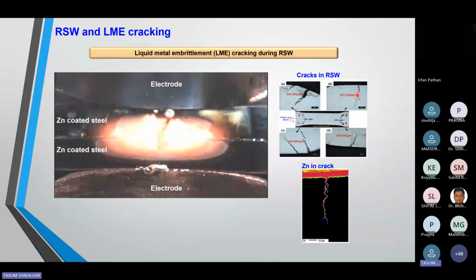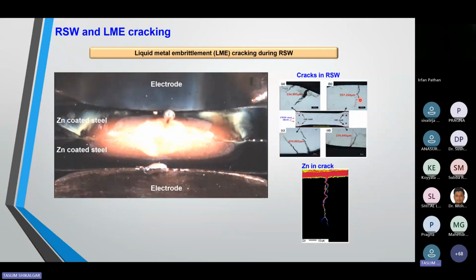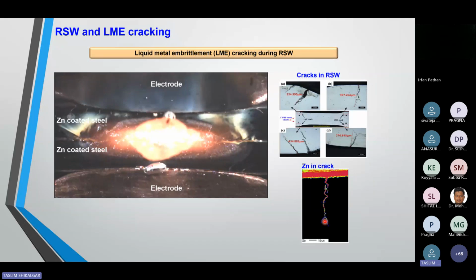So people are testing this type of specimens, these welds, and how much zinc is deposited inside the steels. They are finding empirical correlations. So how can we predict with the help of numerical as well as damage mechanics models how dangerous this zinc is, and how we can avoid this liquid metal embrittlement during this resistance spot welding.